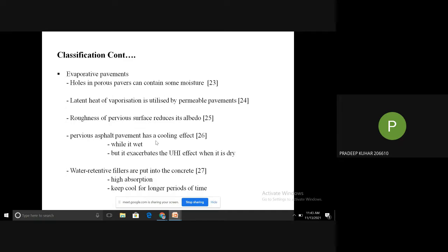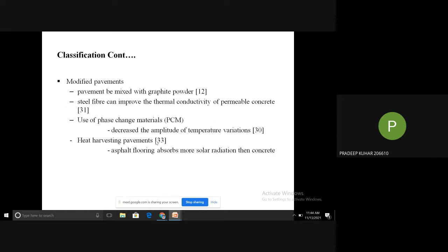Now, if we look at the evaporative pavements, then porous, permeable, pervious and water retaining pavements come to mind. Chen et al. in 2019 concluded that holes in the porous pavement contain some moisture and dissipate the heat energy by evaporation of water and lower the temperature. In continuation of that, Ferrari et al. in 2020 added that permeable pavement also utilizes the latent heat of vaporization. But another study of 2011 depicted that though the water can reduce temperature, the roughness of this porous pavement also reduces the albedo, which further reduces the reflectance. So it can be concluded that evaporative pavements only have cooling effects till they have access to water, and they become dry as they absorb a high amount of heat due to poor reflectance. So we can also use water retentive fillers in concrete to cover this effect.